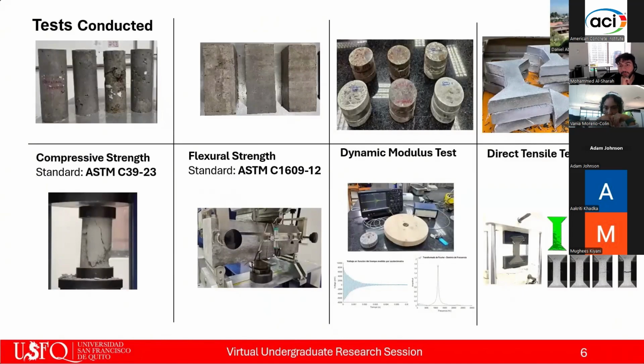Direct tensile strength was measured on dog-bone specimens cured for 14 days. A speckled pattern was applied for digital image correlation, DIC, to capture strain. The tests were performed on a universal machine with custom grips at a loading rate of 0.08 inches per minute.